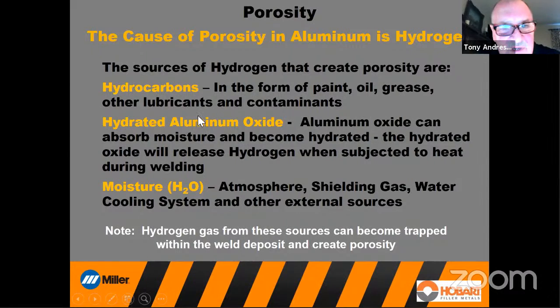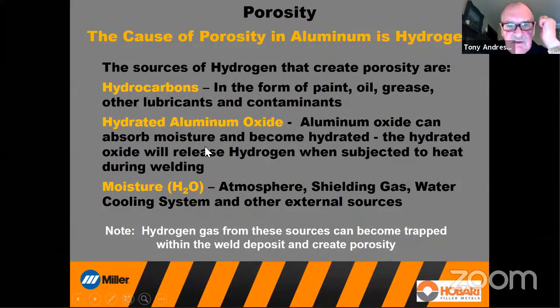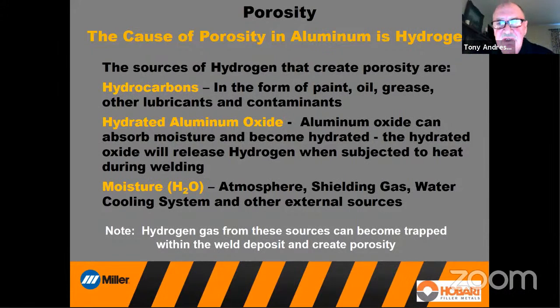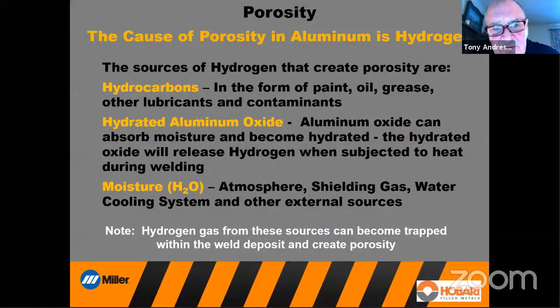The next one is hydrated aluminum oxide. Okay, aluminum oxide, I said it's a strange beast, right? It does a number of things, and one of them is that it can absorb moisture and it can become hydrated. If you weld over a hydrated aluminum oxide, it will release that hydrogen during welding, and that will cause porosity. So you have to remove any hydrated aluminum oxide from the surface of the plate, and you have to make sure that your wire is not contaminated by moisture, right?